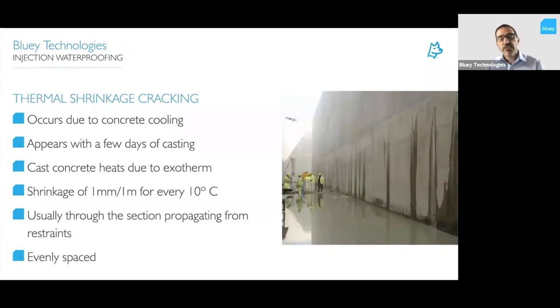Thermal shrinkage cracking, this is a really common type of cracking, particularly in thick structural elements. When you pour large volumes of concrete, it gets quite hot because of the exothermic reaction that's occurring as the concrete is curing. It can reach temperatures up to 80 degrees. And then it sets at that high temperature and it becomes hard at that high temperature. Then over a period of a few days, it cools down again. And as it's cooling down, the concrete will shrink and contract. And as it contracts, it might be restrained, as it is in that photo, by the base slab that it's sitting on. And what happens is the cracks will then propagate off that base slab and up the walls. And that propagation of the cracks will occur over the first few days of casting as the concrete cools.